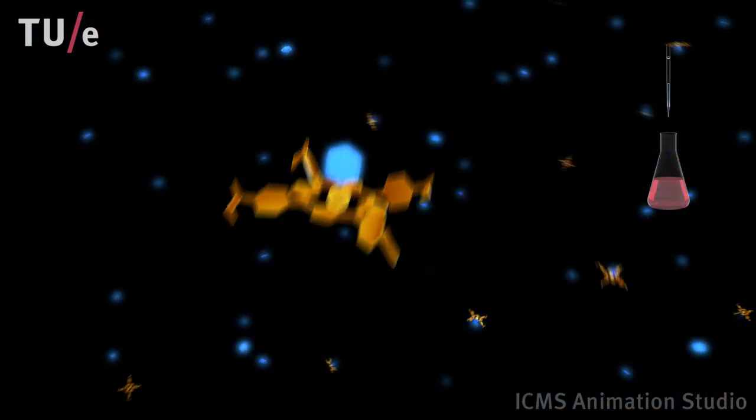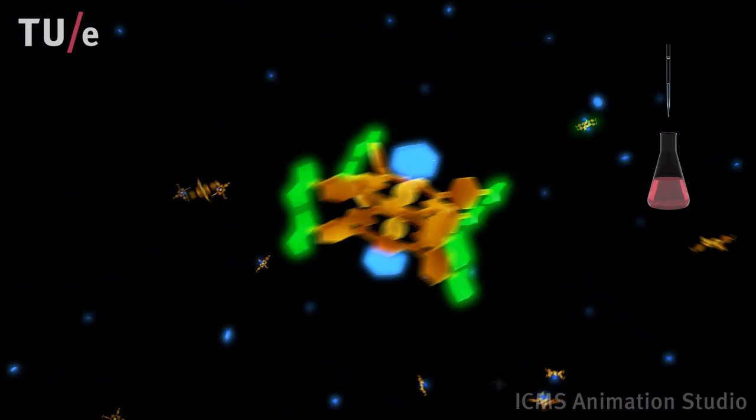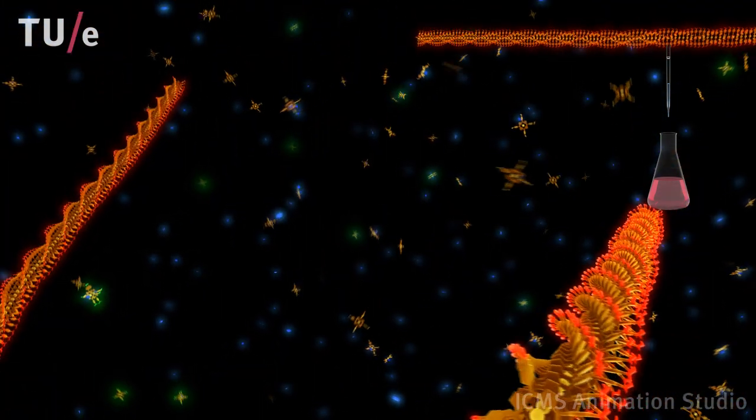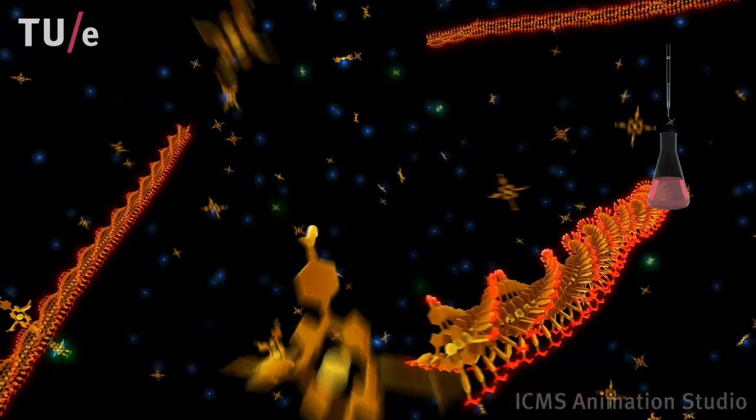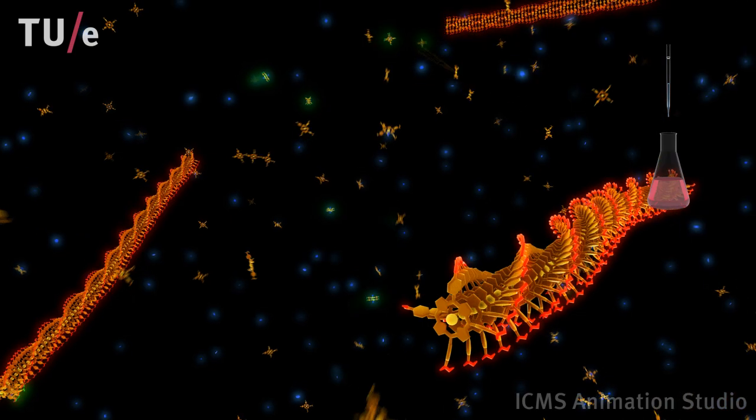At higher amounts of pyridine, the one-to-one complexes form pyridine-capped porphyrin dimers upon the formation of hydrogen bonds. Concomitantly with the formation of these closed dimers, the stacks depolymerize.